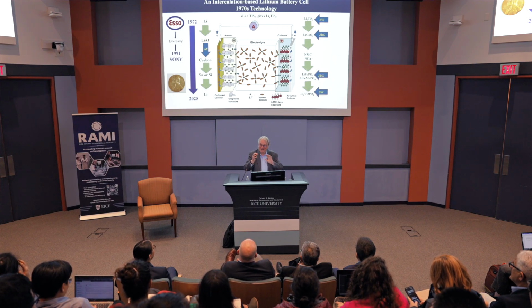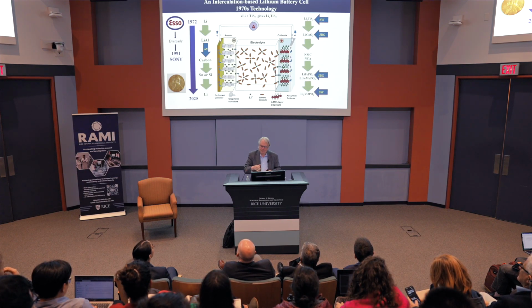They try things that may work. The point is they're all metastable. So the cobalt is 4+. When you take the lithium out, it doesn't want to be 4+. It wants to lose oxygen, and that brings up some other issues. Cobalt is too expensive, so then the field went to a mixture of nickel, manganese, and cobalt.